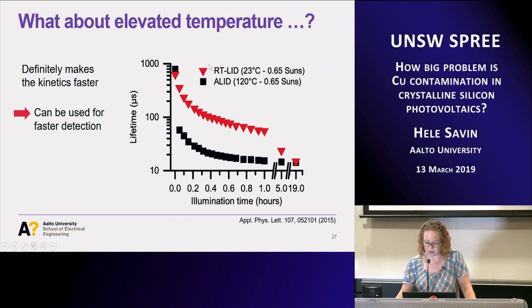So typically the time scale we talk about for room temperature copper LID is, let's say, okay, here we have, please note the time scale, that it takes about 20 hours to stabilize to the final lifetime. But if we increase the temperature to 120, we can speed up this reaction, and we get the same saturation now maybe already in 1 hour. So it certainly makes this reaction faster. And this is of course natural because we just increase the diffusivity of copper.